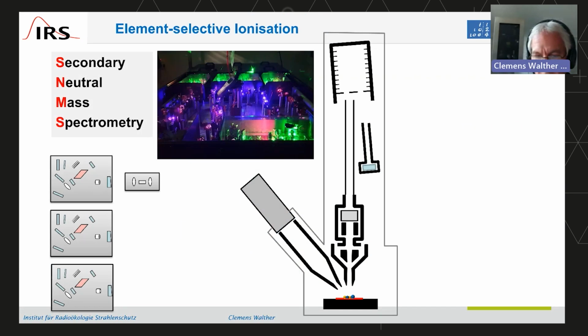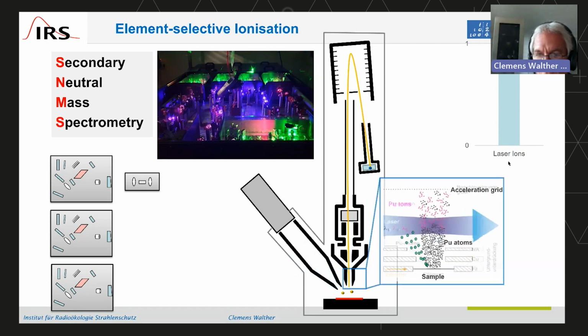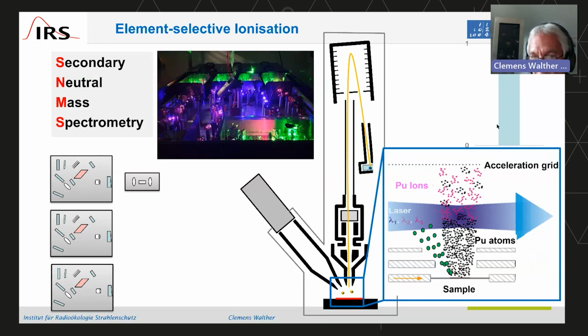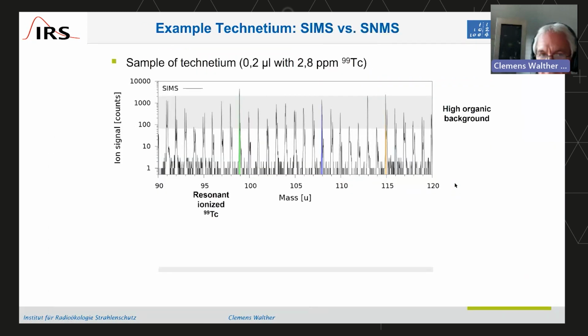We just said that we fired the ions here to the surface. You see them coming here. Then you produce secondary ions by firing the laser. And after you successfully produce these ions, they fly to the TOF analyzer, and you can get a mass spectrum here. So if you blow up that region, that is the laser coming in, a 3-step laser, giving you these nice colorful schemes here. And then you produce your ions that you can detect in your mass analyzer.